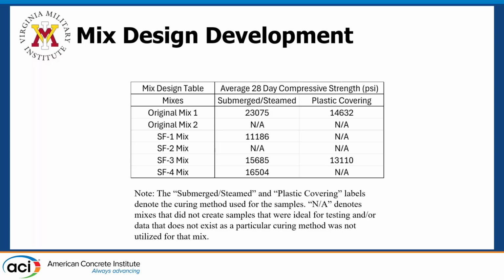So SF3, as you can tell, there's a clear difference in the submerged/steam/plastic covering, and that's what led to SF4 having no plastic covering samples. We made the determination that the submerged/steam apparatus was effectively able to get 28-day strength at about 7-8 days. We had 7-day breaks breaking the same as 28-day breaks. So it speeds up the process, but we found, however, that it's not necessarily the most effective in the long term.